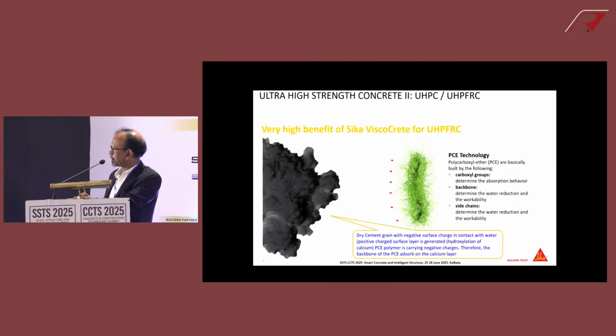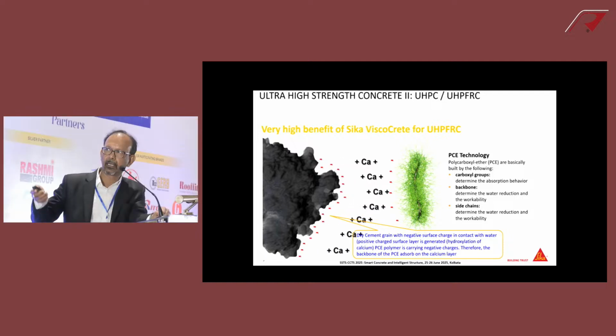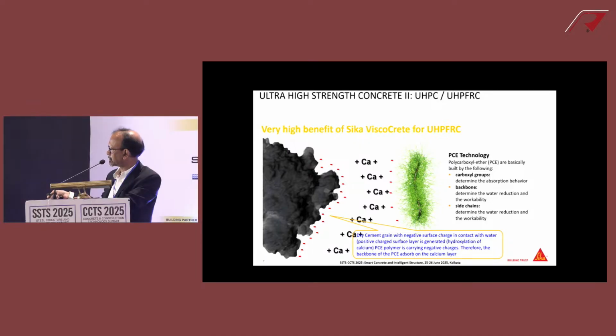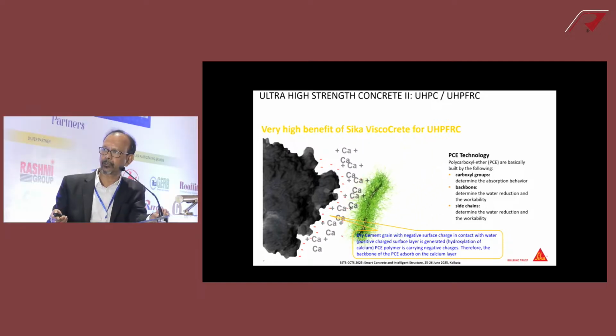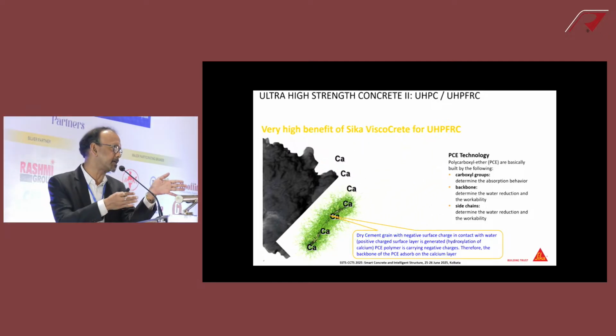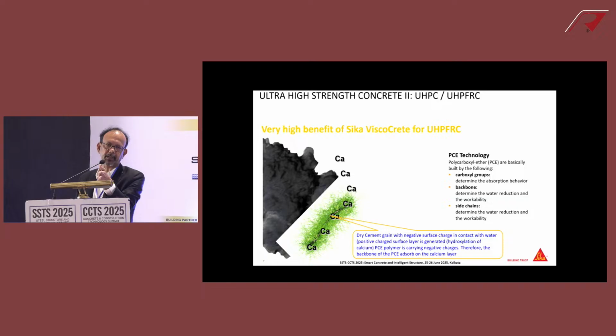So just to give you how the mechanism goes, the calcium ions of the cement, so this is cement, and then you have this PCE technology. This is the long chain, and these are the innumerable side chains. Design, of course, is based on the manufacturer. And you know, like charges, when they are coating the cement particles, repel each other, and that is how you may have more available water for workability.